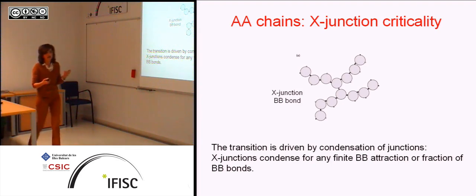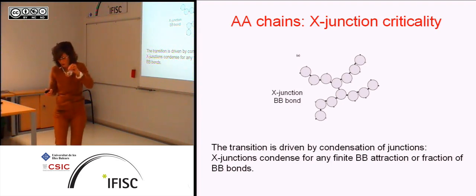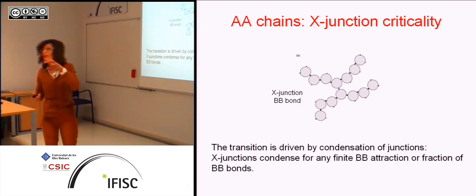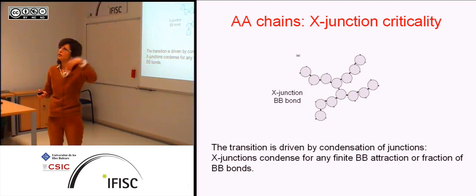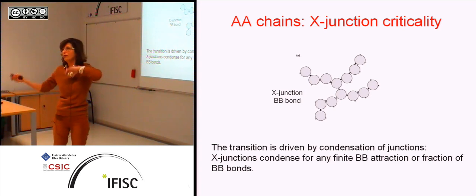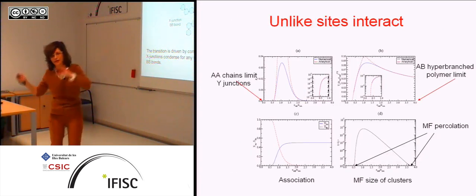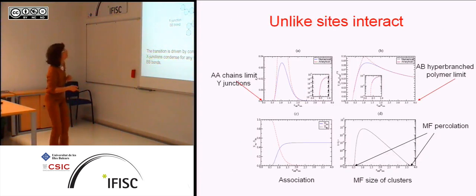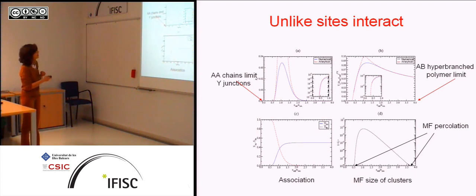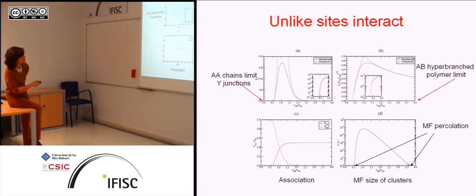Since the chains are not condensed, we can look at this in a simpler way, in terms of the junctions, the defects, and it's the defects that condense. We have a phase which is rich in X junctions and one phase which is poor. We're going to show you that in fact we have two network phases. Okay, this is the other limit. We now have still A chains, no BB interactions, but we let the A's interact with the B. And now the surprise was that the critical temperature actually goes to zero even if the AB interactions are attractive.